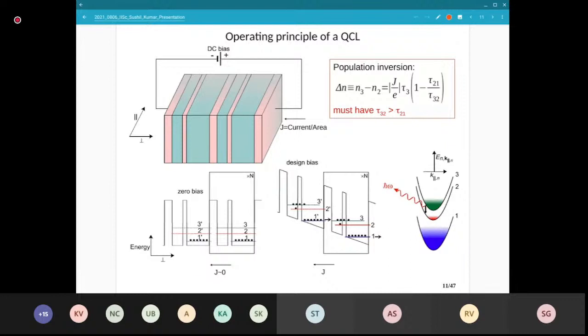So this is a really simple structure. The actual structure is a little complicated. This is GaAs/AlGaAs. So the barriers will be aluminum gallium arsenide. The wells would be gallium arsenide. And these dashed lines are showing the electron subbands once you calculate them. In general, the electrons will be occupying the lowest subband. By n times, I mean in this picture that you have n times this two-well, two-barrier structure repeated. And that n can be about 100, 200.